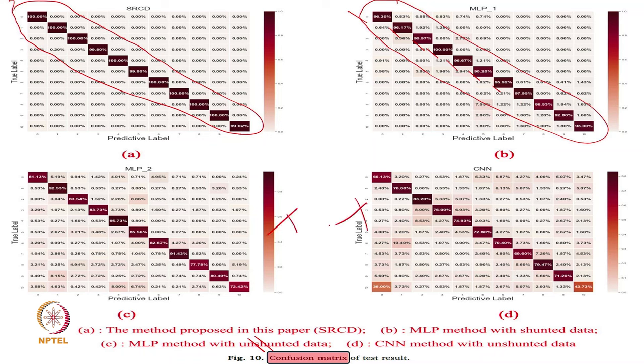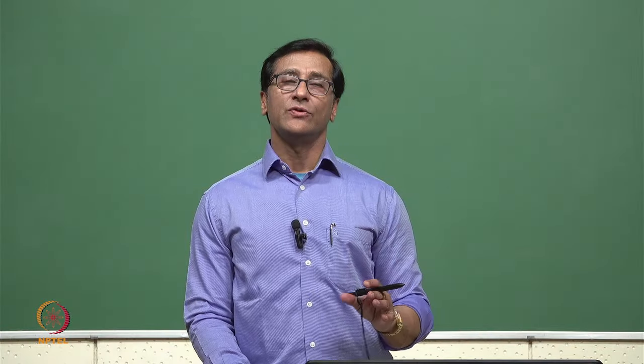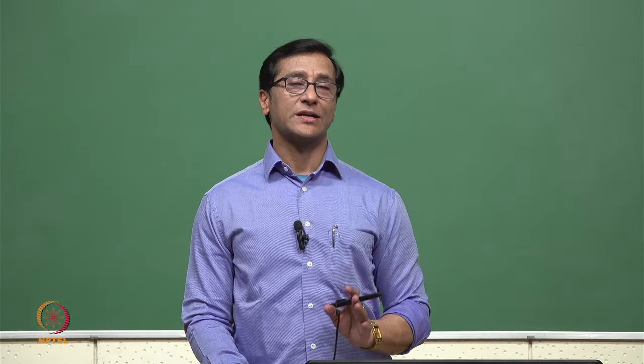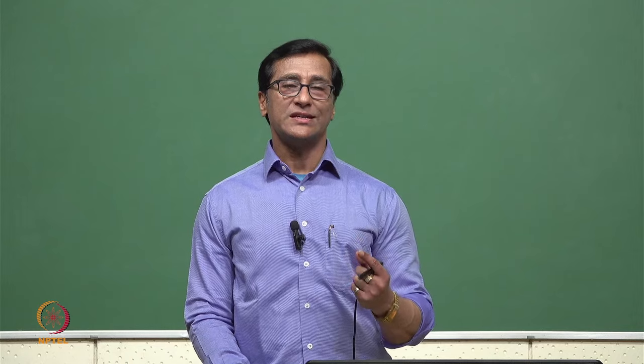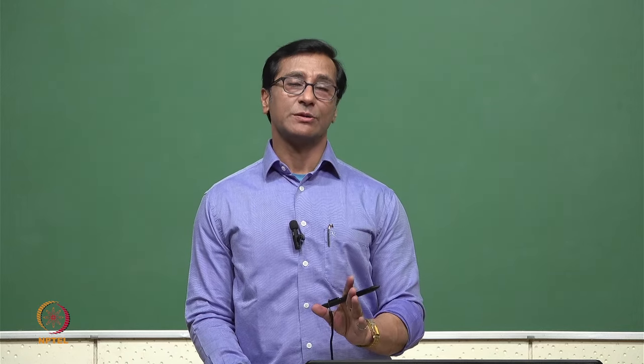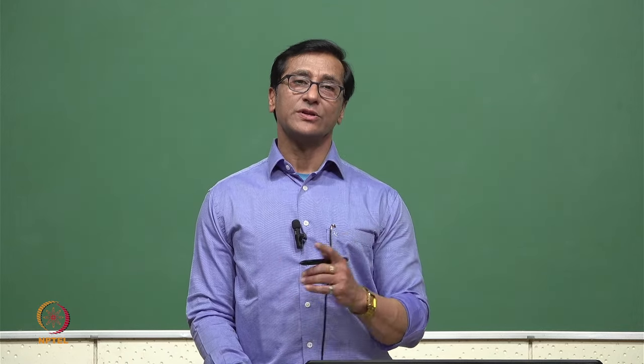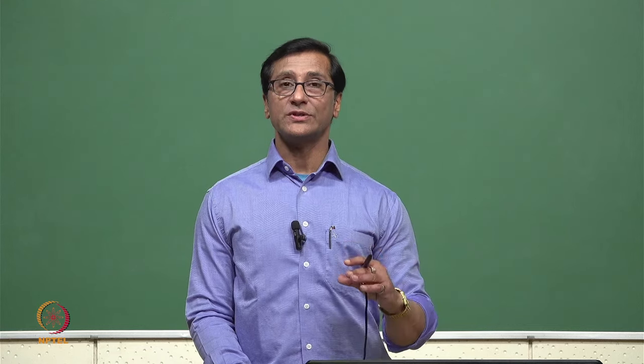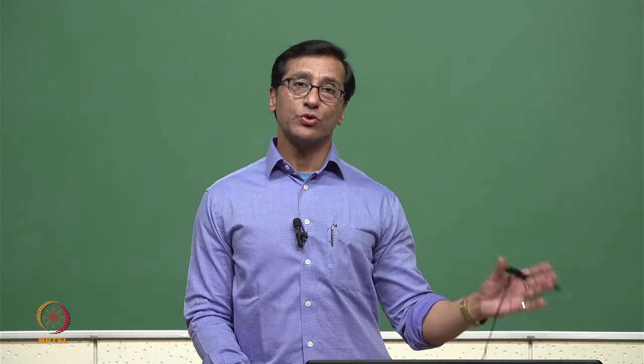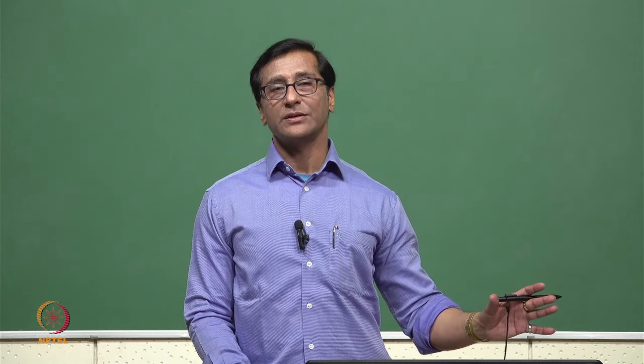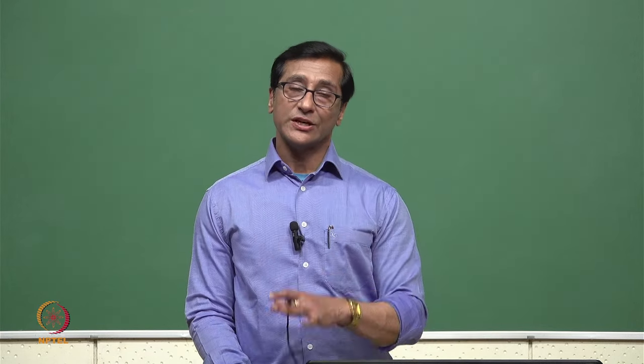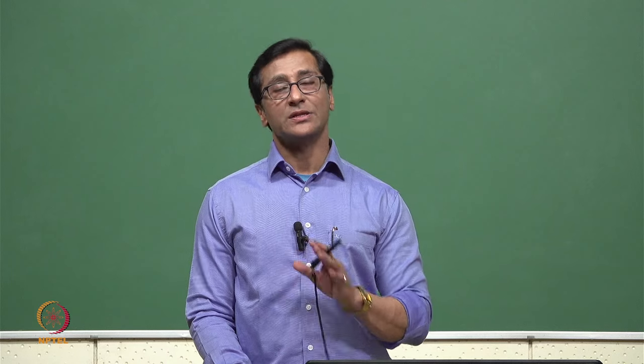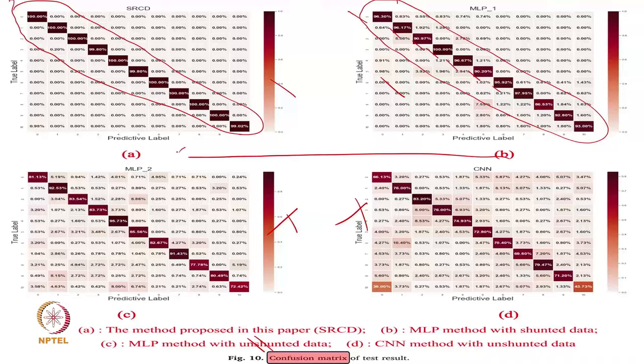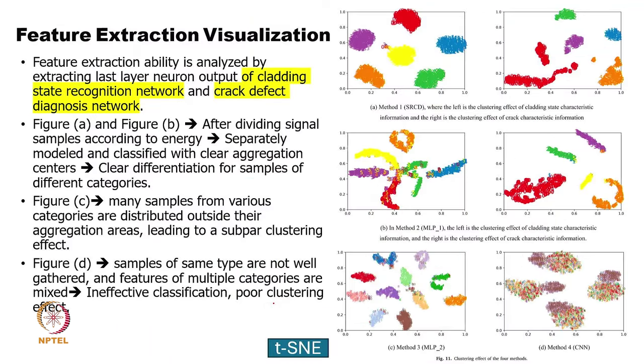So what is the conclusion coming out? Whenever there is a need, we may go with multiple CNN algorithms. Thinking that only one CNN algorithm will give results may not be correct. Every CNN algorithm for the different stages should be different. So here they are trying to optimize a coating process, and that algorithm needs to be different. They are trying to detect cracks in the coating, and that algorithm needs to be different. A and B have been shown from that point of view. Both are giving good results. When only one algorithm is used, results are not good, so it may not be utilized.